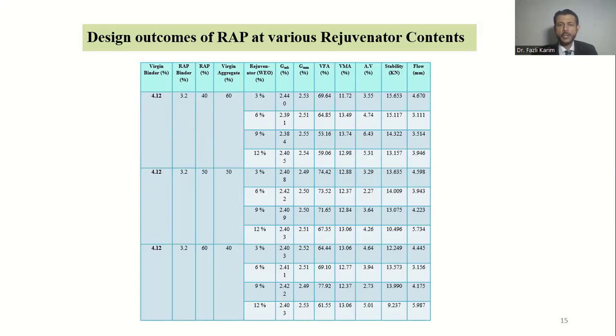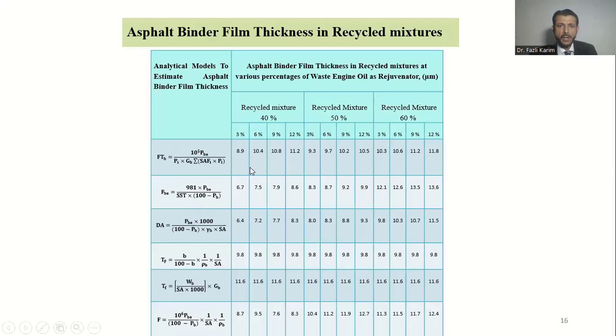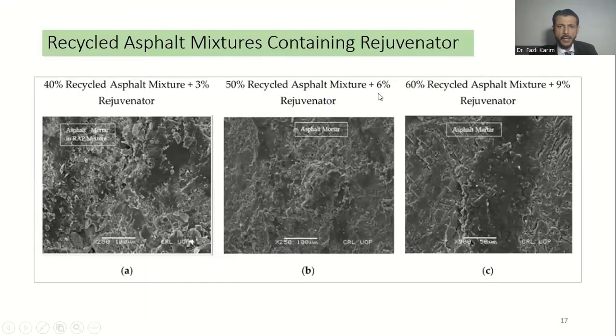And the next phase was to calculate binder film thickness in the recycled mixture using these volumetrics. Therefore, asphalt binder film thickness was assessed for each rejuvenator content and each percentage of recycled mixture using these analytical models. Now, the next phase was to verify these film thicknesses using micro level techniques. Therefore, again, all the samples were thoroughly studied using scanning electron microscope: 40% recycled mixture with 3% rejuvenator, 50% recycled with 6% rejuvenator, and 60% recycled mixture with 9% rejuvenator content.